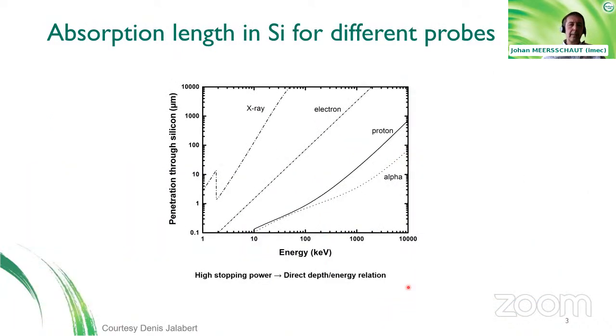On this slide, I show the penetration through silicon for some of the probes that are being considered in the Radiate project. On the left here, you see that X-rays have a large penetration through silicon. This, of course, depends on the energy of the photons. The larger the energy of the photons, the higher the penetration depth through the material.